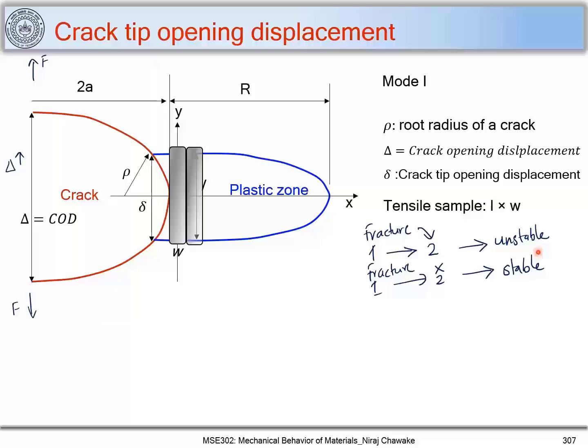crack growth. So we can find this out using the crack tip opening displacement, and an important relation we can find when this crack propagates in a stable way is that the strain energy release rate G is equal to sigma ys, which is nothing but the yield strength, and del, which is nothing but the crack tip opening displacement. So you can refer to George Dieter for finding out how this relation comes. You can use Dugdale models, which we have figured out, for what the R can be in front of sigma ys, and based on these relations you can find out the strain energy release rate. And this is an important relation where G is equal to sigma ys, which is the yield strength of a material, times del, which is nothing but the crack tip opening displacement.